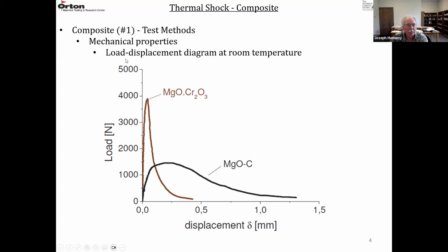When you run a load displacement test on this type of setup, there are a couple examples here. This is the MgO carbon composite. This is an MgO chrome material. You can see the MgO chrome material is stronger. It's a higher peak on the load. It's more linear, but then it has a pretty abrupt failure, so it's much more brittle than the MgO carbon composite. The MgO carbon material has a lower load. It's more nonlinear, a less brittle, more ductile material. The area under this load deflection curve is going to be higher. It takes more energy to propagate a crack in these materials.